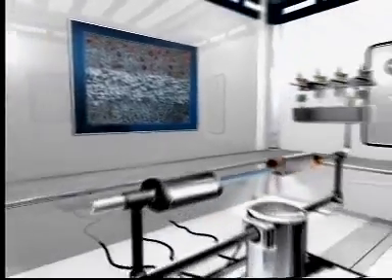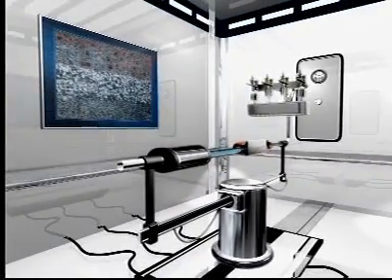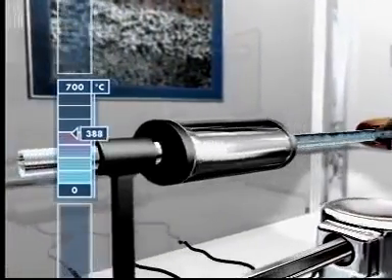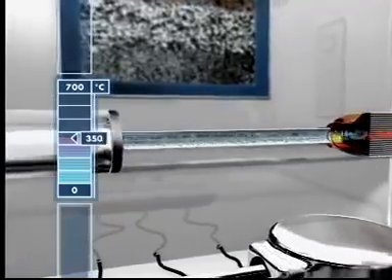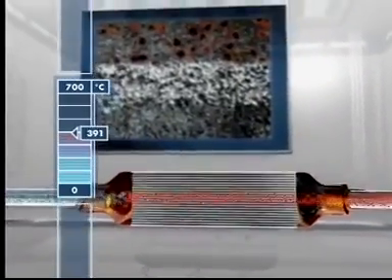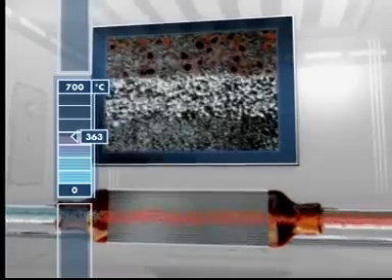Let's have a look at the way the Volkswagen development functions in detail. The position of the filter near the engine, with exhaust gas temperatures of over 300 degrees Celsius, ensures that during normal driving operation, through a reaction with nitrogen dioxide, the built-up soot is continuously dissipated — a so-called passive regeneration.